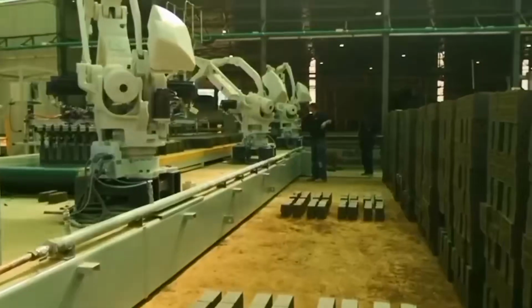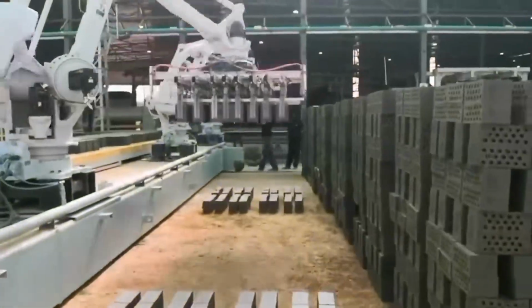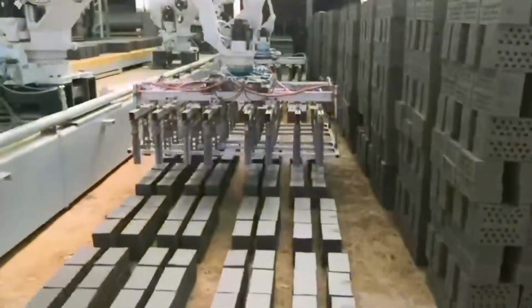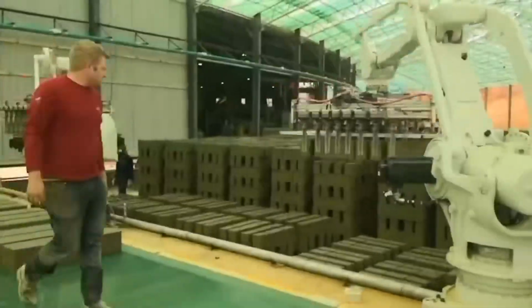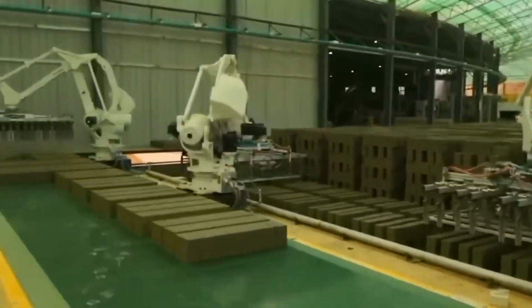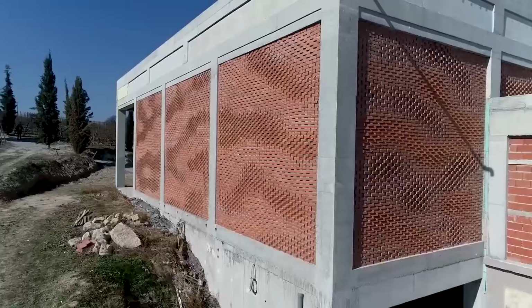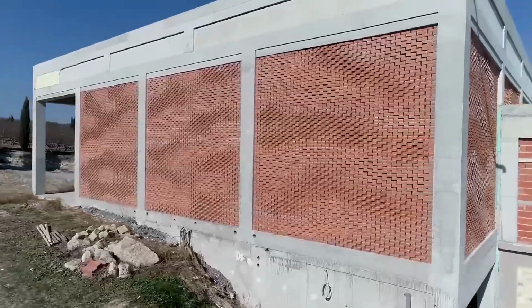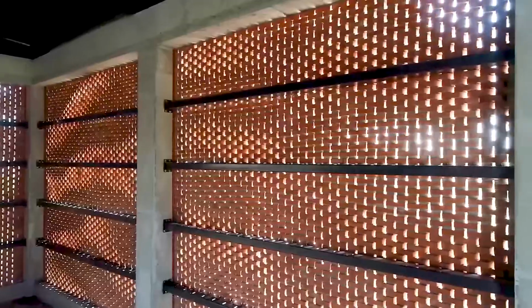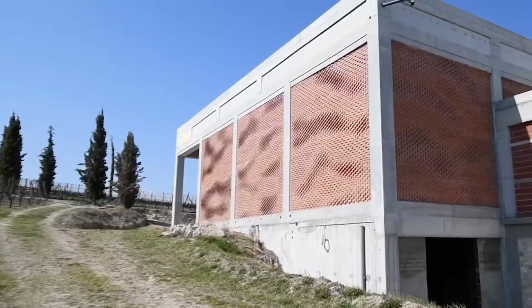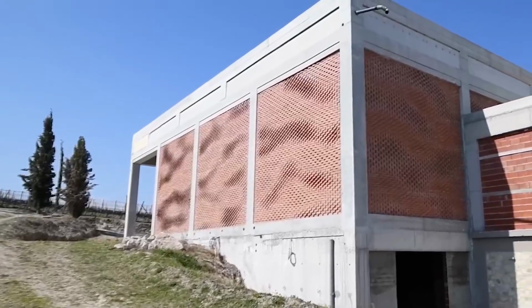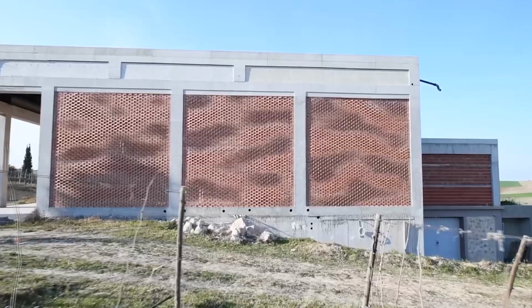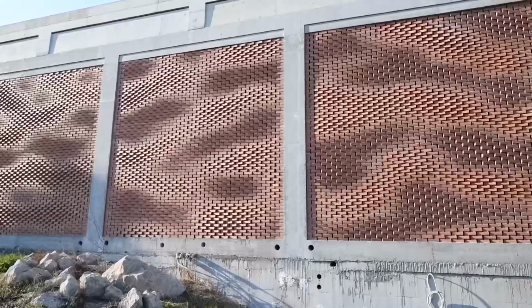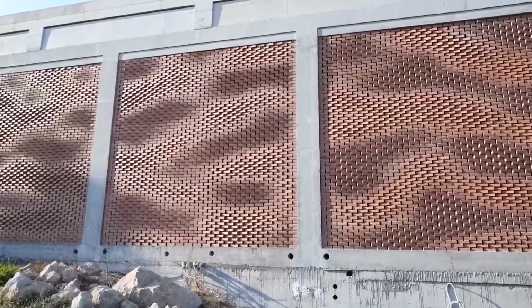Ceramic bricks are more porous and can absorb significantly more water than quality concrete blocks. This high absorption can lead to problems such as efflorescence, which are white stains, and in very cold climates, the risk of damage from the freezing of absorbed water. Because of this, they require more care on the construction site with protection from rain, and even in the specification of the type of coating and finish.